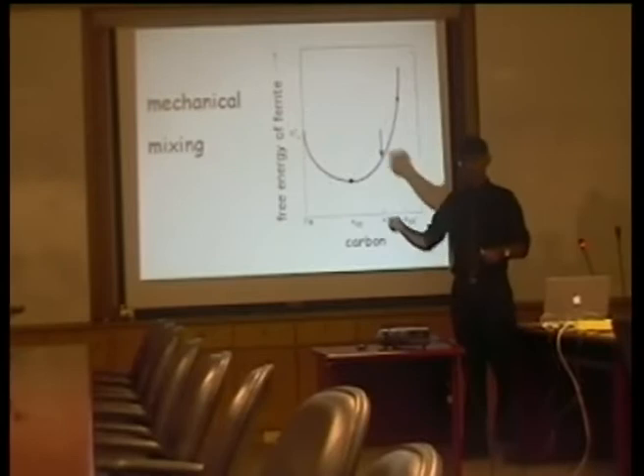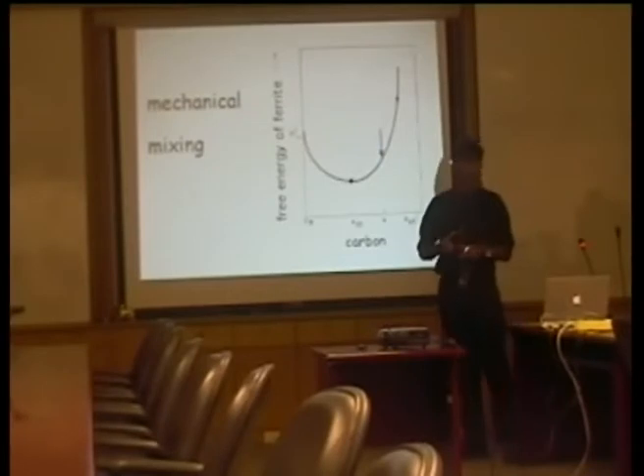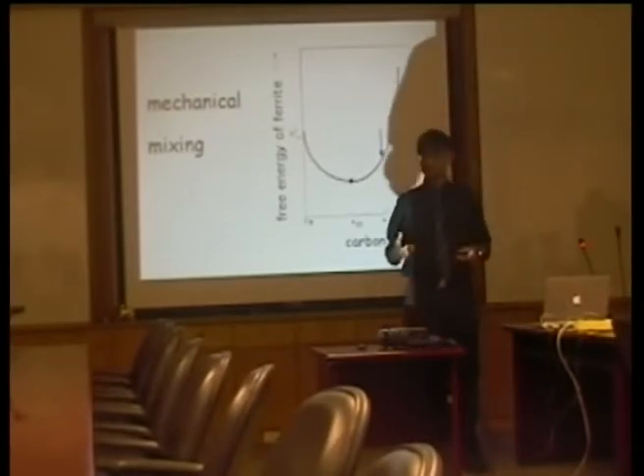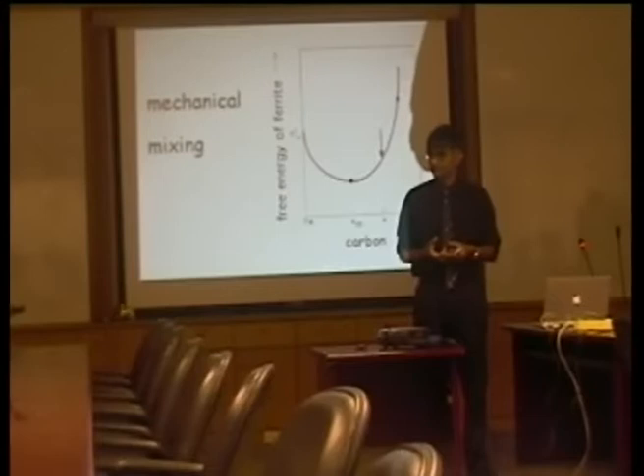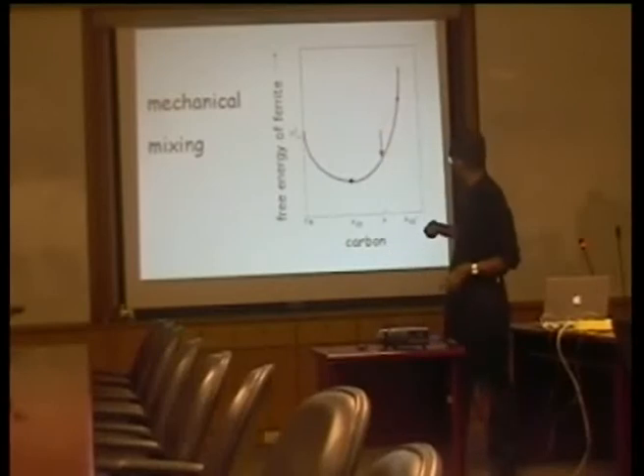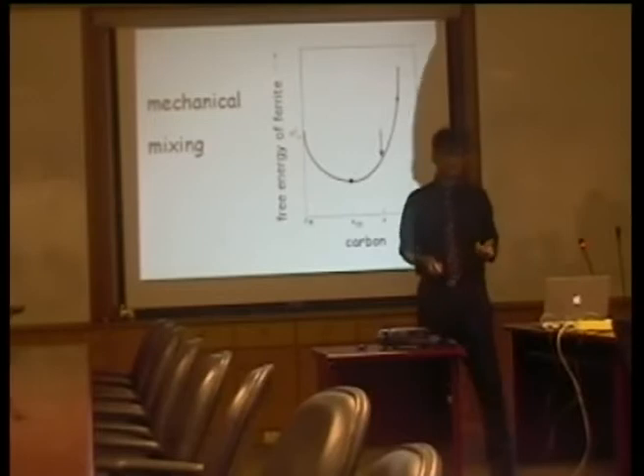So it's favorable for the martensite to lose some carbon and for the ferrite to gain some carbon during this process. And that's the reason why we get this mechanical mixing, even though the whole deformation is happening at room temperature. You get a reduction in free energy if you mix up the martensite and the ferrite.